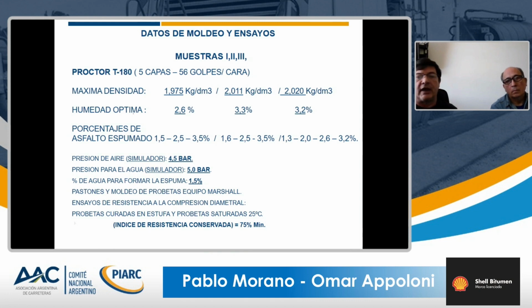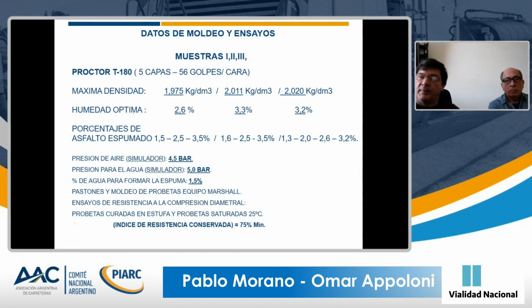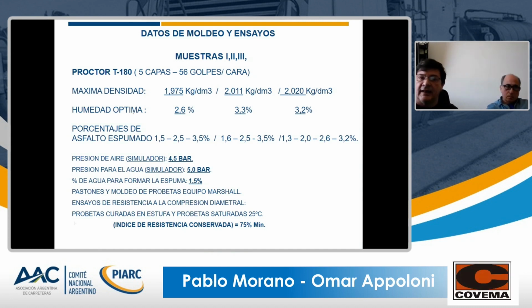We did the tests, and here we have the maximum densities for 5 layers and 56 impacts, and we have 1,975, 2.011, and 2020 regarding density. Then we have the moisture, and we evaluated 3 types of foamed asphalt.